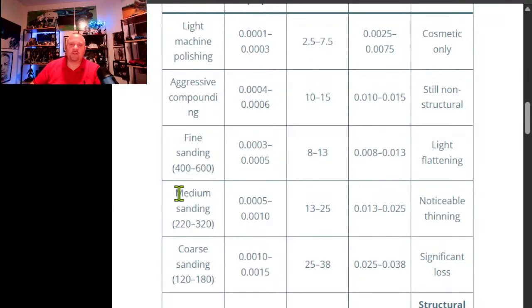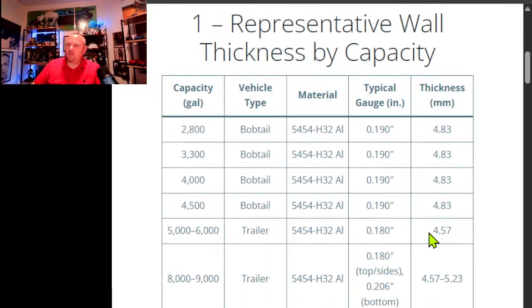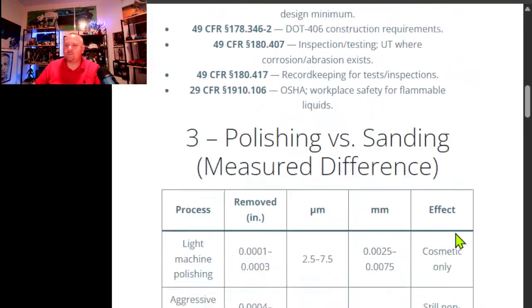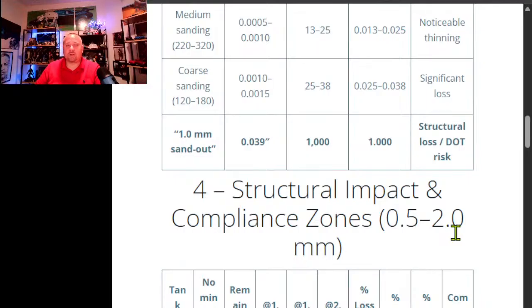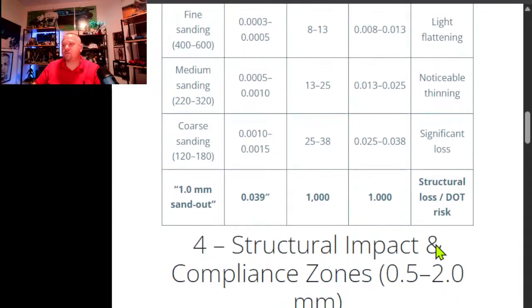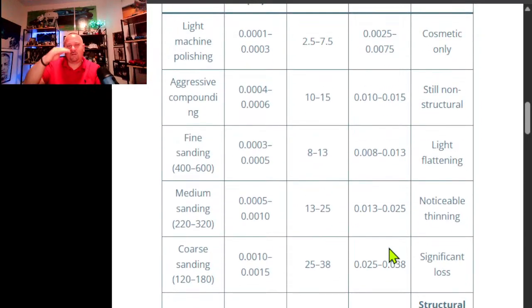1.3 millimeters thick. Now if you come back up here, you're looking at one of these brand new, even on a trailer, is 4.57 millimeters. Now if you have something that is 1.3 or 1.5 millimeters deep, which typical pits can run at least a millimeter, and we're talking not so much pitting, but gouges from road debris, sanding, from sandblasting, from rocks, things like that. It could easily be 1 millimeter. Well, in order to get that smooth and to remove that, you're removing material. Now, I'm going to go back to that. So hold on to that.